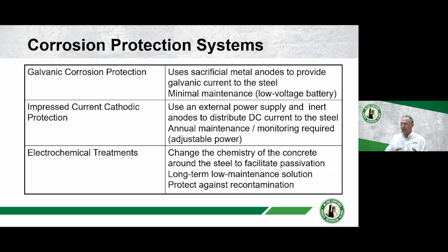You want to, in concrete, just use zinc, because even in concrete, zinc will passivate, and it won't give you any current if it is not active. So what we do is we activate the zinc with an alkali material. So typically you're going to have a small localized corrosion protection system for concrete repairs using galvanic corrosion protection.